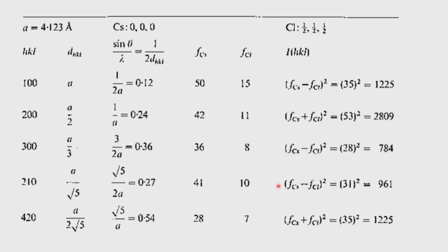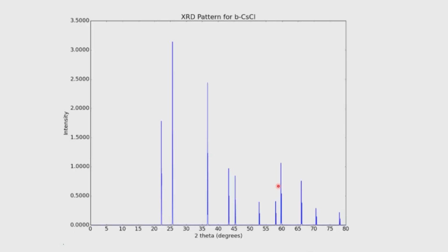However, if I had recorded a powder pattern, I would have got this powder pattern. This is for reality. So you have the cesium chloride sample and you powdered the cesium chloride crystal and recorded the powder pattern. Of course, this is a simulated pattern, so it does not give you any widths. In a typical powder pattern, there is a certain width associated with it. This we will all discuss when we go to powder diffraction methodology, which is very crucial, particularly for the pharma industry people, to remember that there will be a certain width with each of these peak positions, and that is very crucial. So effectively, this is the intensity we will get when we put the cesium and chlorine in known positions and calculate the corresponding contributions to individual reflections.